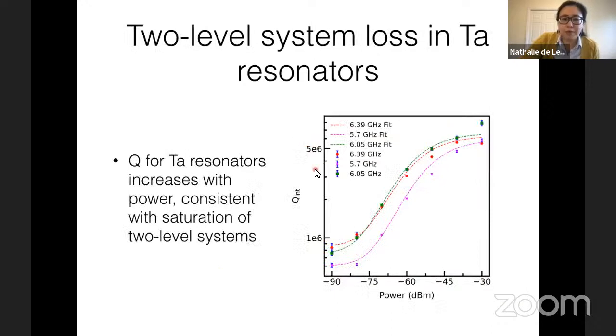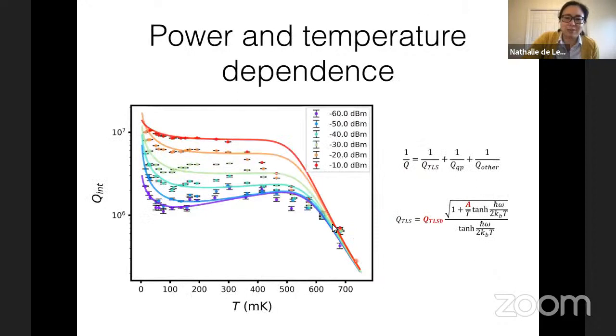So here's an example of one of these data sets. What we see is that the quality factor for these resonators really changes dramatically with power. This is characteristic behavior of losses that are dominated by 2-level systems, because you can saturate the 2-level systems. Okay, just totally full disclosure, I was completely expecting to enter this field and find that 2-level systems explained nothing about the behavior of superconducting qubits, just because it seemed too easy. But it turns out that it explains almost everything about the behavior of our resonators.